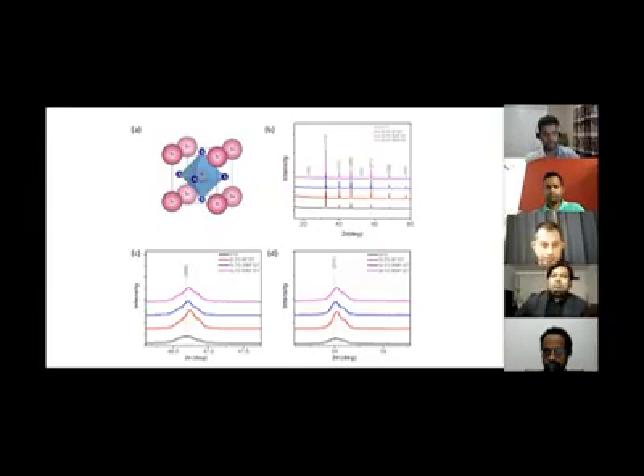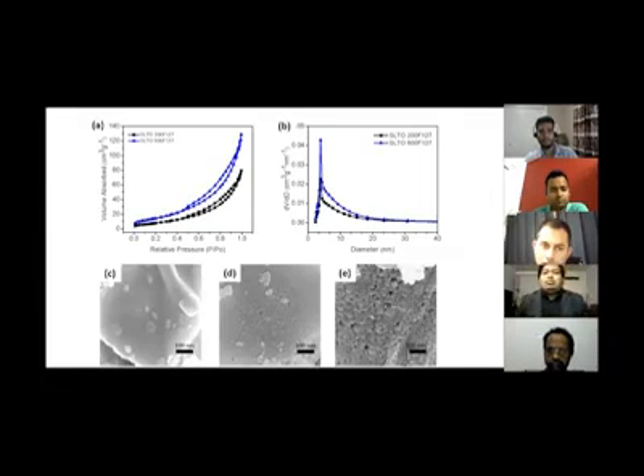So we did the XRD to find out the phase of our material, and here we can see the peak shifting is actually confirming that our material is doped by lanthanum successfully. And then we did BET analysis to find out the pore size distribution inside our material, and we can see the SEM images also. Nice, we can see some nice nanometer holes in our samples.